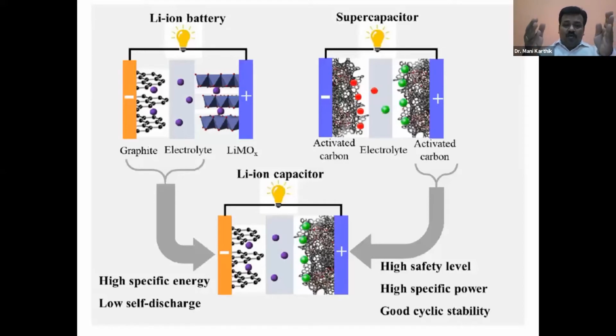So if you take one electrode from, for example, graphite from lithium ion batteries, and another electrode from activated carbon from the supercapacitor, by combining these we can achieve high energy as well as high power. So this is a hybrid capacitor. One electrode is from the lithium ion chemistry, battery behavior, and the other one is from the supercapacitor behavior. By combining these we can achieve the hybrid capacitor, which sits in between. It gives a high energy density compared to the supercapacitor. It gives a high power density compared to the lithium ion battery.